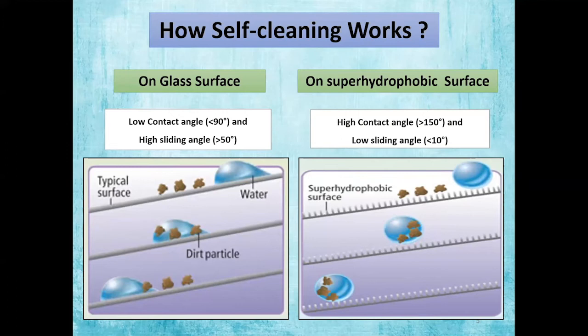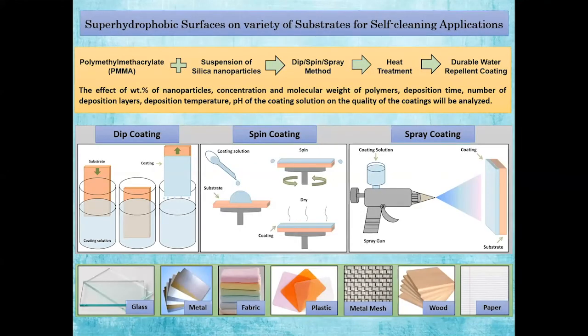On a normal surface, as the contact angle is very low and the sliding angle is very high, the hardly sliding water drop cannot catch all the dirt particles while sliding. But on the superhydrophobic surface, on the contrary, the adhesion between the water and the surface is very low, and hence the adhesion between the solid surface and the dust particle is also low. So the rolling water drop can easily catch all the dust particles and roll off, making the surface self-cleaning. So what we did in our research is that we used different polymers and silica nanoparticles.